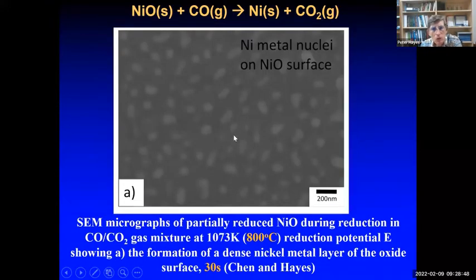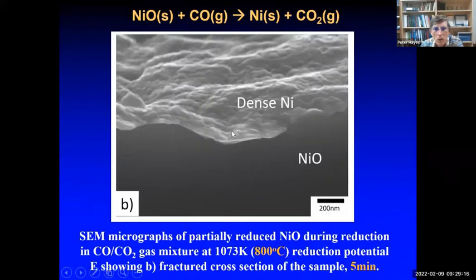If we go to a higher temperature, 800 degrees centigrade, and look at the surface after a very short time, we find the darker gray is the nickel oxide, and these lighter gray islands on the surface are actually nuclei of nickel metal. So we have nucleation of individual nickel metal on the surface, and as time goes on, we find that those dense nickel nuclei grow and eventually seal off the surface here and form a dense nickel layer.